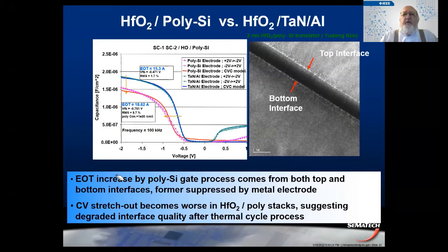I threw this in just to illustrate that high K and metal gate is absolutely necessary. And it's one of the cooler things, to show a CV curve. You can see that the one on the polysilicon electrode is rather flat and barely turns up on the positive voltage side. And the metal gate, even though it's simply a tantalum nitride aluminum electrode, is nice and crisp, with a clean effective oxide thickness of 15 angstroms. So with high K and metal gate, you can pass that 20 angstrom limit for regular, I shouldn't say regular, because that's silicon oxide type of oxides, really high quality, but the CV just stretched for that. So you need high K, you need metal gate.